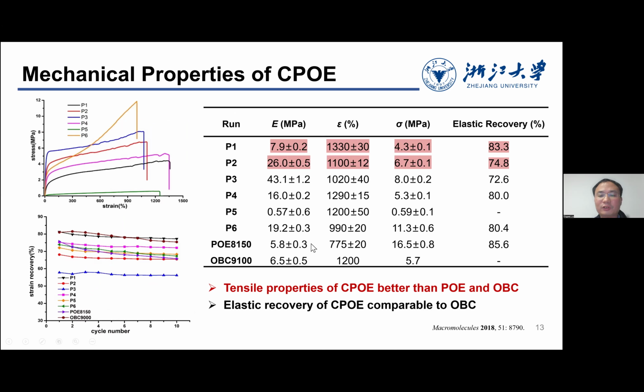We find the properties are better than those of commercial POE, for example, POE 8150 from Dow, and also the olefin block copolymer, also from the Dow Chemical Company. You can see here the modulus, elongation at break. They're good, better than this commercial product. And also the elastic recovery is comparable to the OBC products.